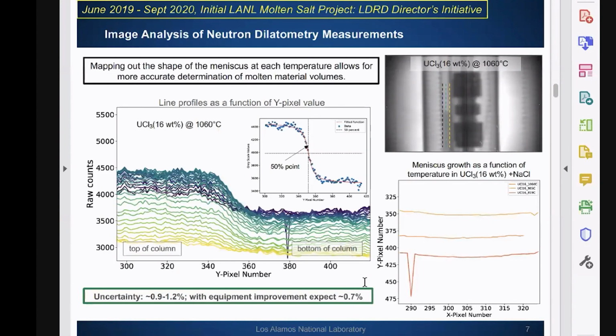And so with this slide, I just wanted to talk a little bit about how we do this image analysis. Initially, we just used it for straight up measuring the sample height change, but we now have developed this technique to fully map the volume of each salt studied. This is done by carrying out image analysis to identify points of contrast with high resolution. So what you want to look at, you can follow the yellow line here. It's going along the wall of the capillary. You can see that the contrast doesn't change much, it stays pretty flat.